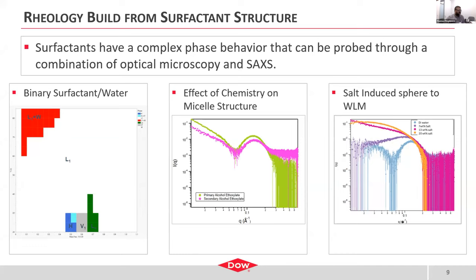So surfactants, like I said, are these amphiphilic molecules that have a hydrophobic tail and a hydrophilic head group. That hydrophilic head group can be, for instance, a sulfate anion. It can be a cationic quaternary amine. It can be a polyethylene glycol oligomer covalently attached to this long chain hydrophobe, oftentimes a hydrocarbon, a C8 to C16 hydrocarbon.